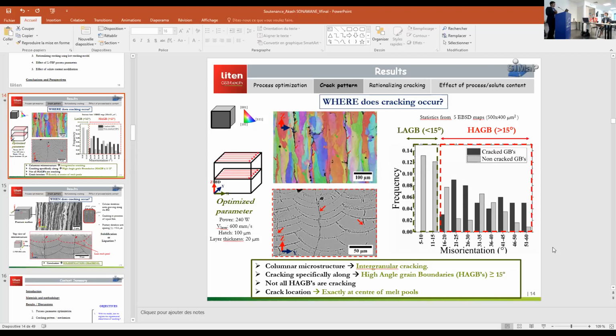Even if we look at the Sindo Kou model, for example, he also looks clearly at the region between the grains, the grain boundary region. When the two grains are growing towards each other, the region between them and the liquid which is feeding that region, if it increases, can have an effect on the propagation of cracks. So if we look into that aspect, I agree, as you pointed out correctly, why not, once you have initiation, have cracking all the way along.